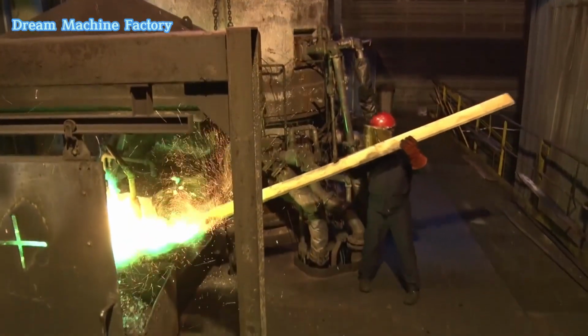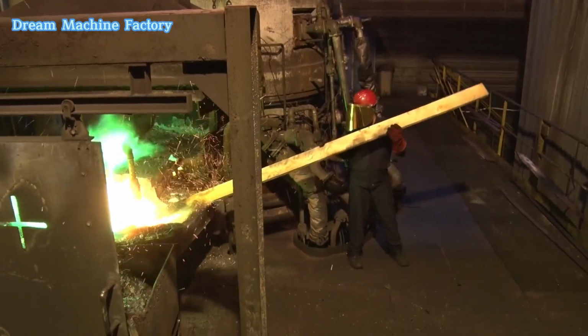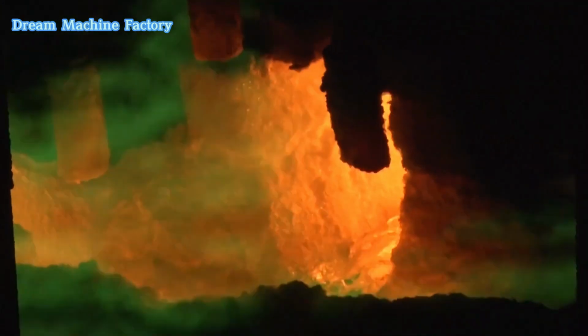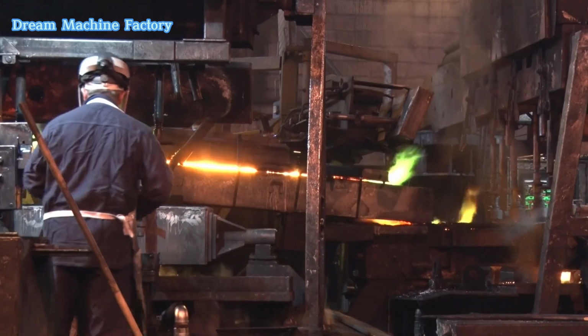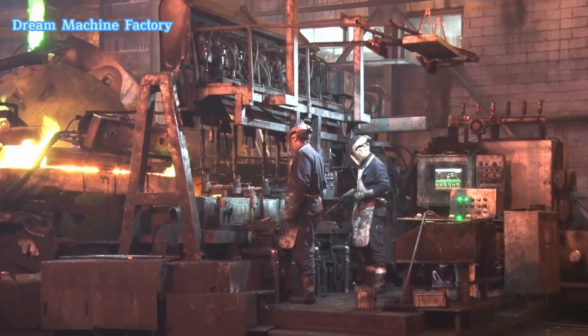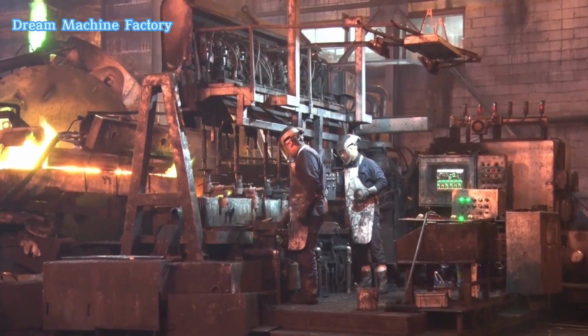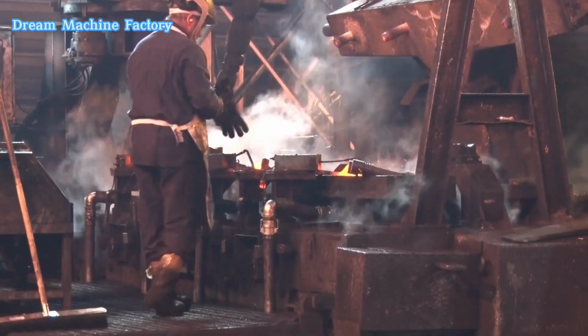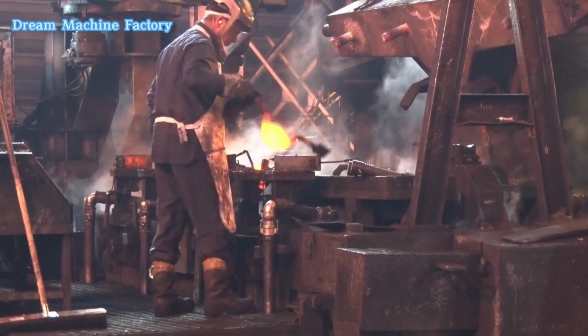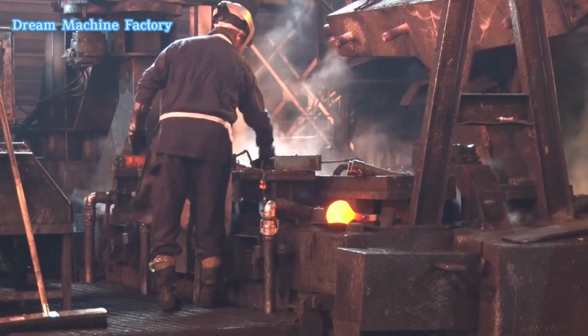Gas burners heat the metal to temperatures above its melting point, 1083 degrees Celsius. The molten copper then flows through channels and is poured into a water-cooled mold to form billets, solid cylindrical bars approximately 10 meters long. This rapid cooling solidifies the metal quickly, and the chemical composition is tested before each casting